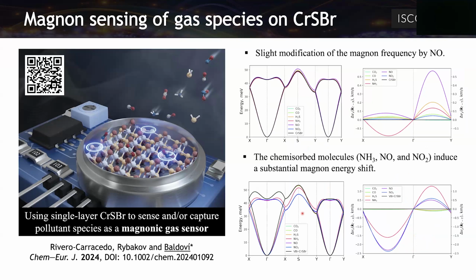And then we wanted also to check what happens in the magnons, to test it with magnon transport, for example. So we have here that when we have the pristine material, there's some effect for the NO, an increase in the group velocity, but the effects are not very drastic. But when we take into account the vacancies in the bromide atoms, we can observe clearly that the magnon dispersion is changing in the material.